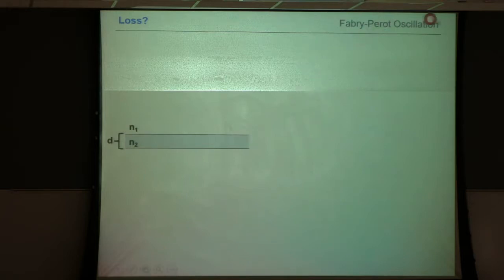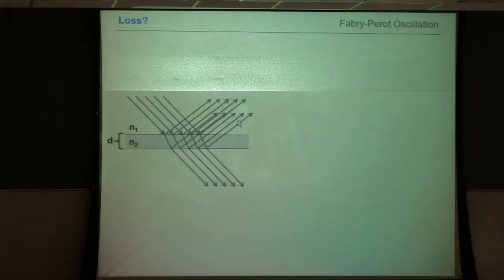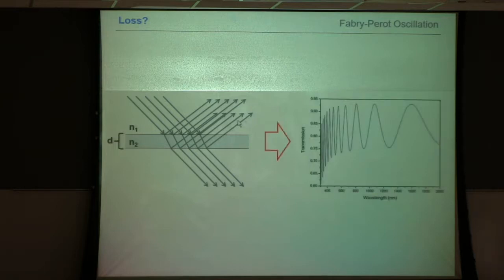How do you measure this? A very simple method is using Fabry-Perot oscillations that you can deduce from simple UV-Vis measurements. So in case you have a film in an environment with a different refractive index, you will have interference, constructive and destructive ones, and they will give rise in your transmission spectra to these types of oscillations. So these are really the Fabry-Perot oscillations, and we can easily learn things from them. From the height, we learn about the refractive index contrast. The higher the contrast, the larger is the intensity of these oscillations. From the width, we learn about the thickness of the film.